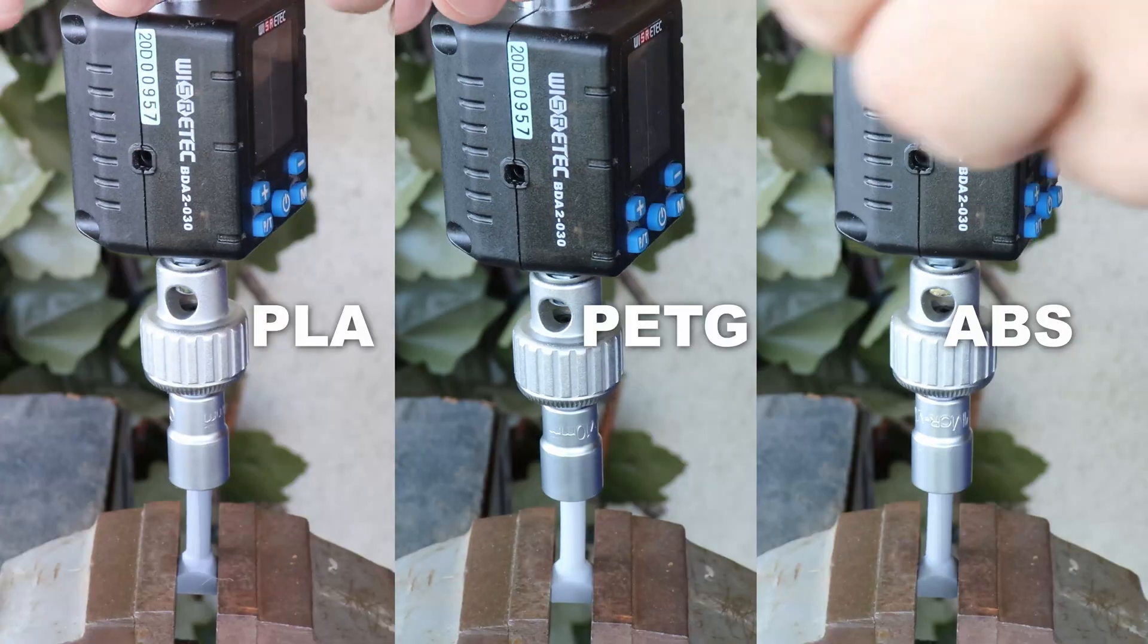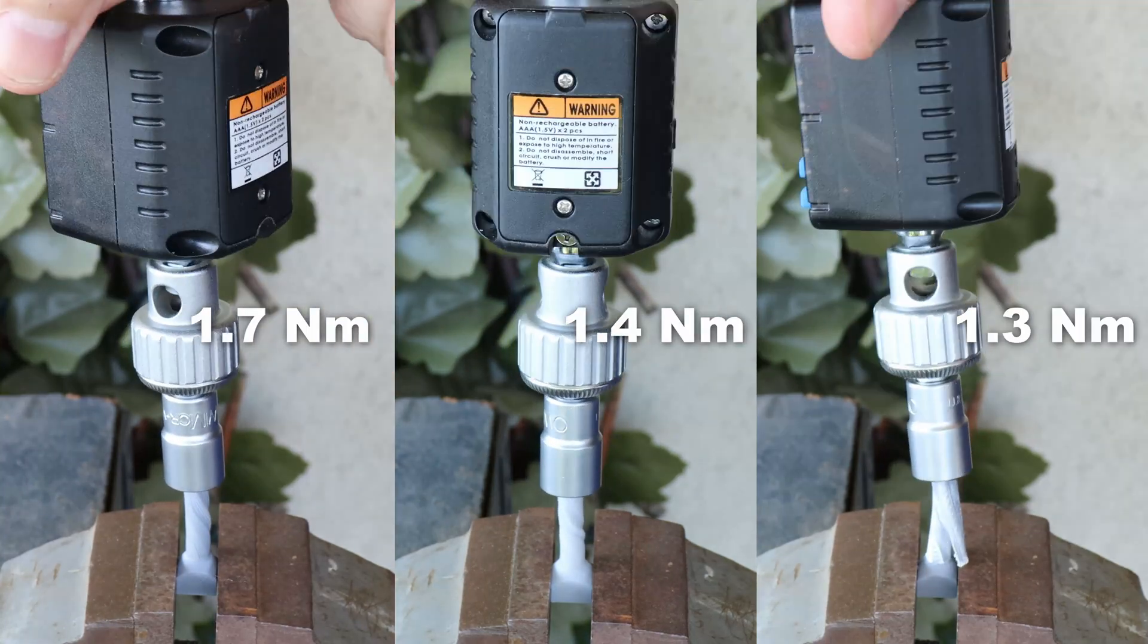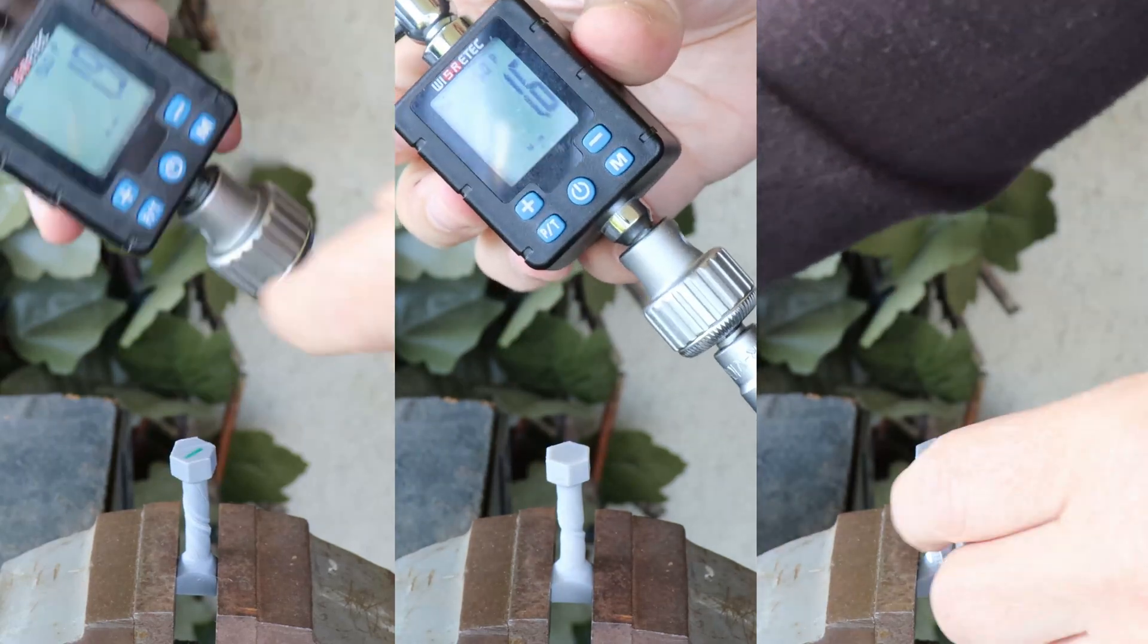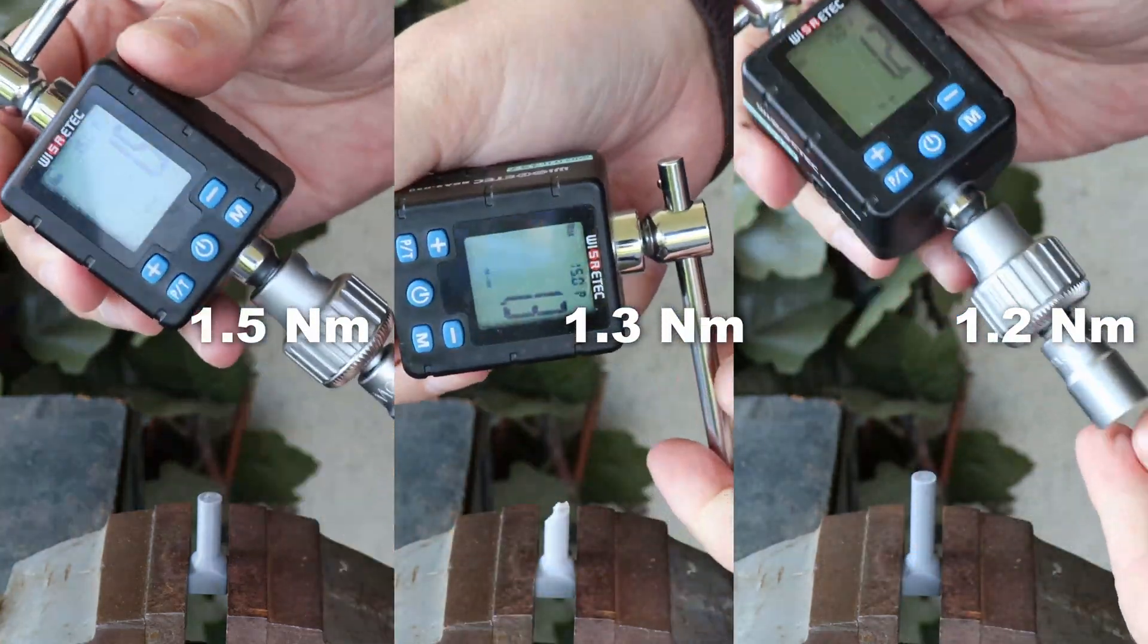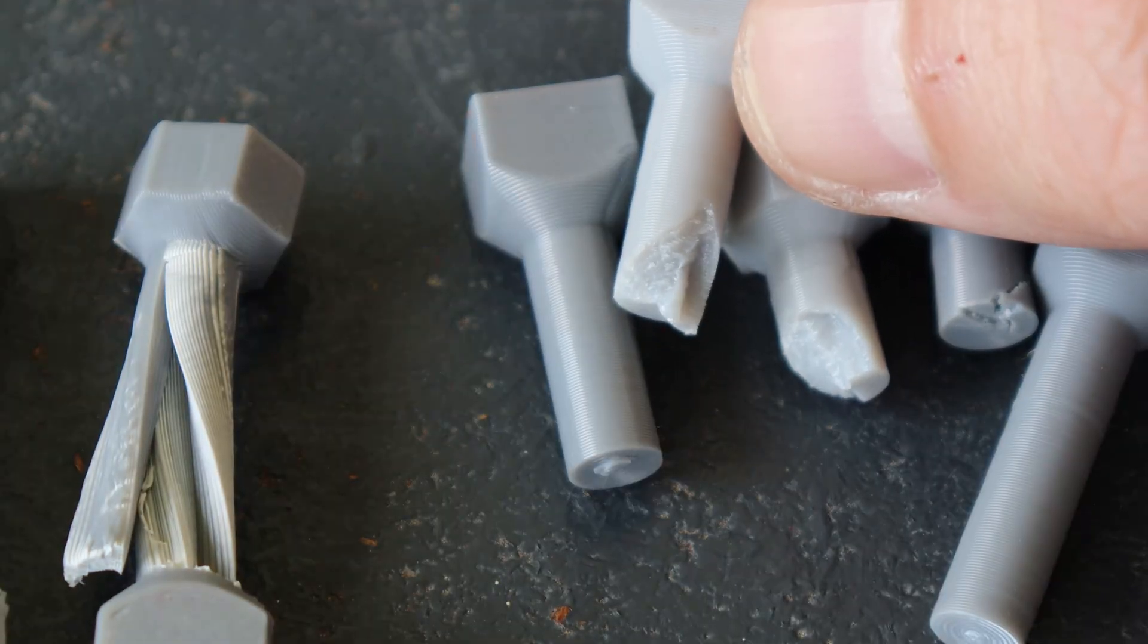The torque or twist test with horizontally and vertically printed test objects. I'm starting with horizontally printed and recording the load at 90 degree rotation and the maximum load. Then the vertically printed test objects—they break suddenly so I can record only the maximum load. When I see a break like this, this is typical sign of good layer adhesion. For horizontally printed objects, the ABS broke a little bit differently.